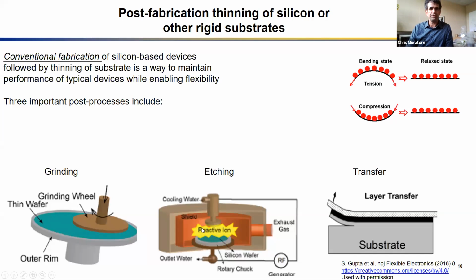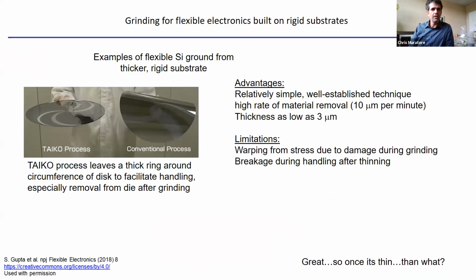But if you want a very precise thickness, or if you want to reduce the amount of damage done on the surface, because a grinding process is going to introduce all kinds of dislocations, etching can be a more gentle way to make your wafer thinner. One way that we'll focus on a lot today is layer transfer. You just find a way to tear the material off of a surface. Maybe you grow the material on a surface with some kind of sacrificial layer underneath, or you sacrifice a substrate. You choose a substrate that's easy to cleave, and you tear the material off and make it thin that way. We'll talk in more detail about how to get to some of these.